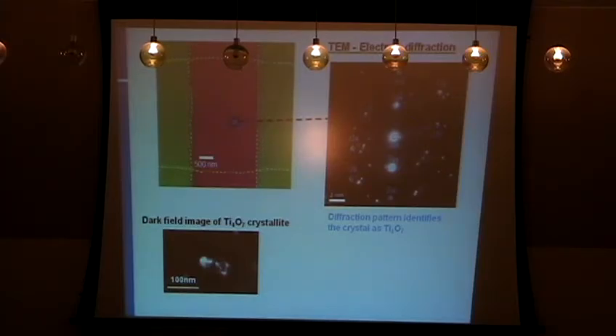Question: Do you have any idea about the thickness of the high oxide layer on top? So we don't know the exact thickness of it. From some electrical data from Julian Borghetti, he showed that in the on-state, the conduction is actually a tunneling conduction, as opposed to an insulating conduction. So we've got a model that's a very thin gap there. And so in my measurements, of course, this is a top view of the device, not from the side, so you don't actually see that gap. We'd have to cross-section it.